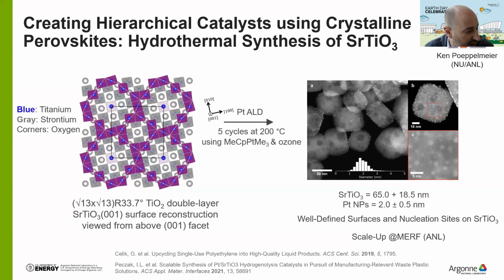And talking with my colleague, Ken Poeppelmeier at Northwestern, he has this very nice nanocuboid of strontium titanate. Strontium titanate is a perovskite. And what is very interesting about this particular perovskite is that the crystal structure of the strontium titanate matches the crystal structure of platinum nanoparticles. That means that the platinum-surface interaction is very, very strong.